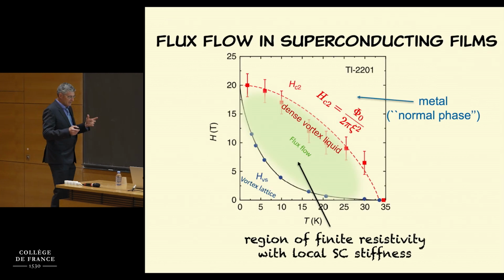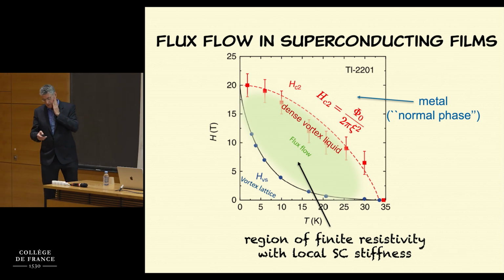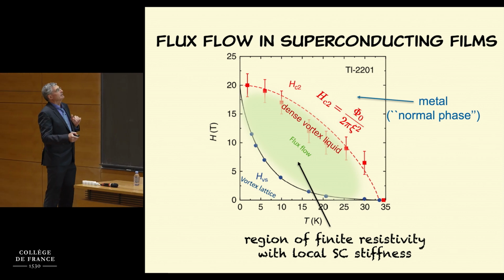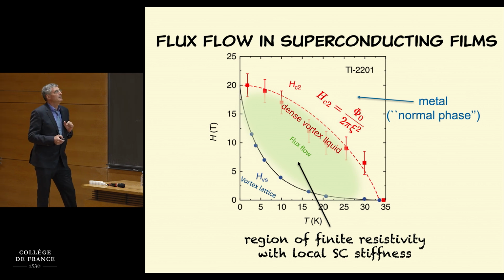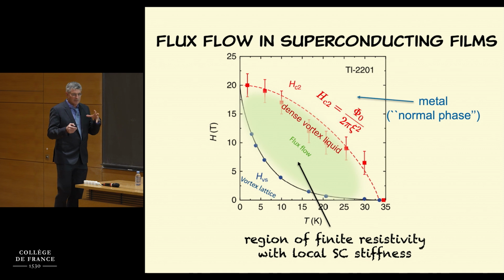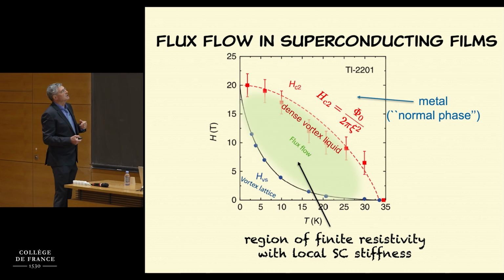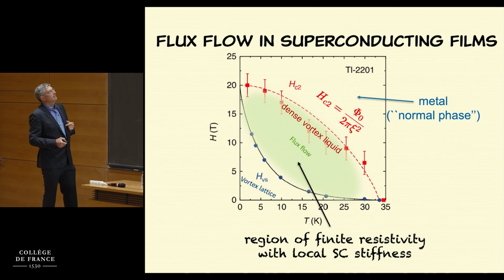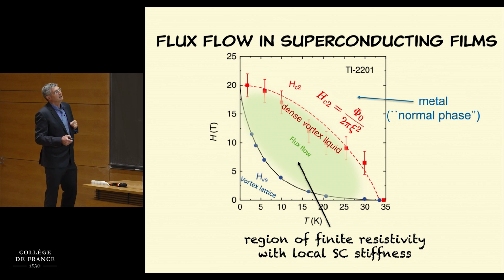And now you look at materials, and many materials have this phase diagram. This is like a high TC cuprates, but it exists in many systems. You have the magnetic field and the temperature, and you have the vortex lattice phase. But if you make the magnetic fields too large, or you make the temperature higher, the vortices will start moving. That lattice will melt. It will still be incompressible, but it will have relative motion of the vortices like an incompressible vortex liquid. In this regime, you get a finite resistance. So this is not superconducting. In fact, in terms of transport, it looks very similar to a metal.